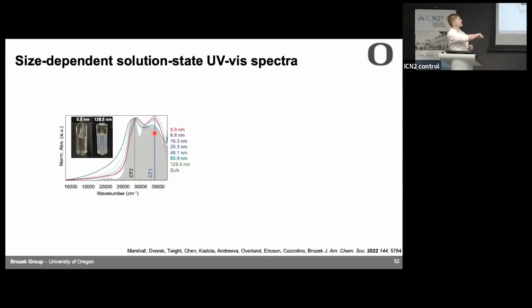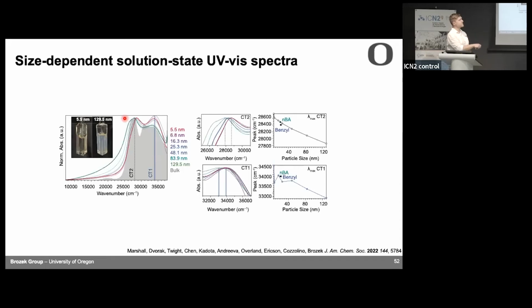The gray data, this is the bulk iron triazolate. All the color traces, these are all different sizes. And so we can focus on the different sizes, and we saw something pretty strange. So these are the 2 different charge transfer bands, these 2 bands here. And we can plot their energy as a function of size. And they redshift. So this is exactly what you see in the quantum dot literature.